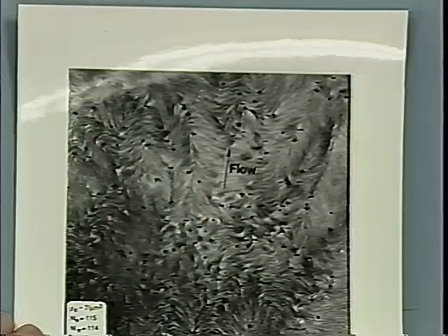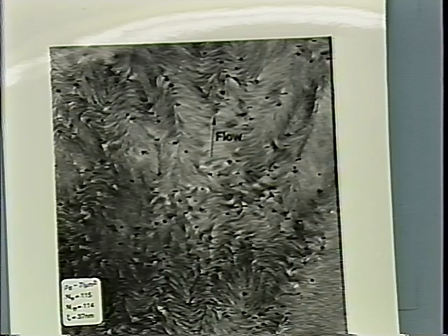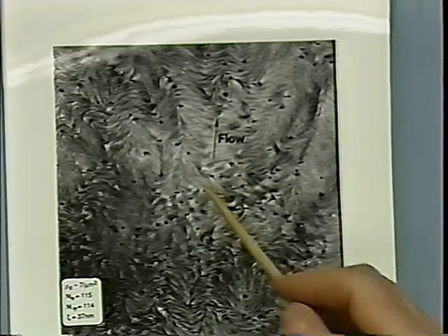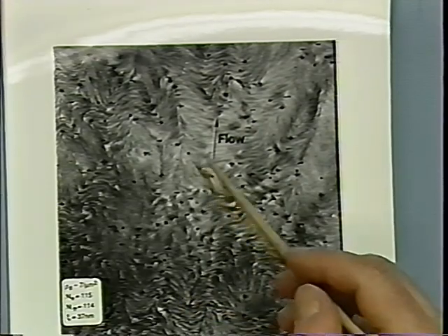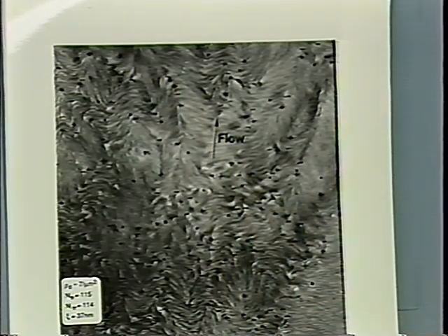Steve Hudson with Ned Thomas produced interesting structures on very thin films of liquid crystal polymers, and they were able to stain them by a crystallization method. You can see the plus defects and the minus defects coming in pairs and being very densely spaced in that material. So imagine this occurring not only on a surface, but in 3 dimensions.